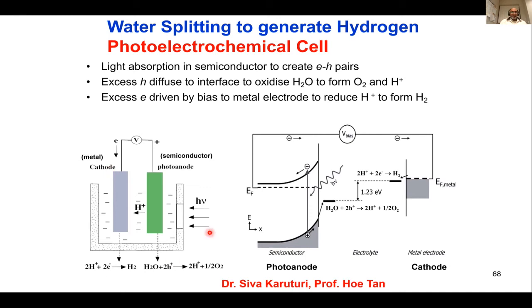Say, for example, you take water and put in some electrodes, a cathode and a photoanode. The cathode could be a metal like platinum, and the photoanode could be a semiconductor. If you shine light on top of this semiconductor, you create electron-hole pairs, and the holes will come and oxidize water, and the electrons will go there and reduce the protons to generate hydrogen. So it is essentially a clean energy source, using water, splitting it into hydrogen and oxygen, and using hydrogen as an energy source. And again, this work is driven by my colleagues, Dr. Siva Karuturi and Professor Hoe Tan, for example.